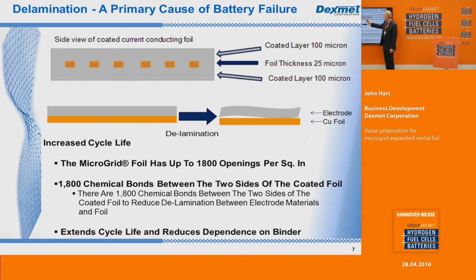The point we're trying to make here is with porous foil, we've got over 1,800 pores per square inch in that foil. It's more than 50% open area, so that you've got a strong bond between the different areas to hold that foil to both sides, and therefore we believe that the indications we're getting from cycle life is that this has a great deal to do with extending the cycle life of the battery.